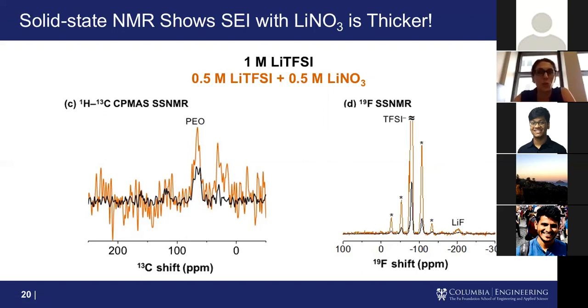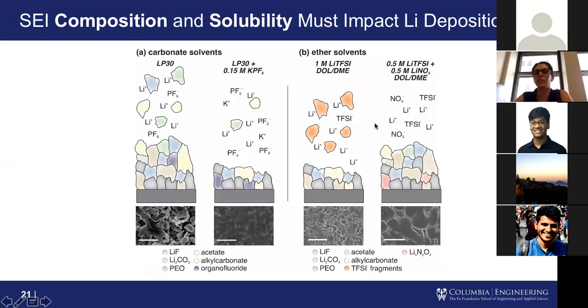So this is very weird, especially given what I've just told you about the KPF6 additive case in the carbonate electrolyte. Because what this means is that when we have nitrate present, we actually have a much thicker SEI. But what that's telling us is that it actually isn't always a bad thing to have a thicker SEI. So maybe this isn't totally goop that the lithium ions have to swim through in order to get to the lithium metal anode. Maybe what matters most is having less soluble decomposition products and instead optimizing the composition of this layer.